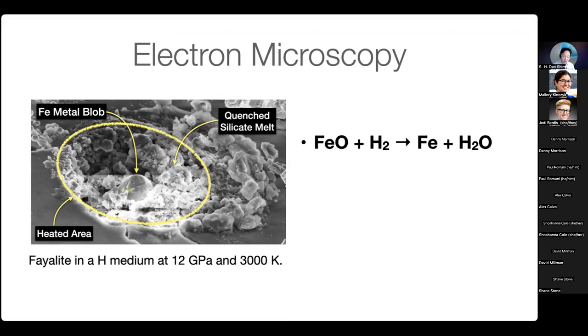To summarize all this into the chemical reactions, we find that oxidized iron reacts with hydrogen and forms iron metal with water. And silicon oxide or silica reacts also with hydrogen and reduces to metal and forms H2O. What is important to note here is that because silicon is oxidized to 4+, while iron is oxidized to 2+, when silicon is reduced to metal, it produces twice more water. And then if you combine the fact that much of the iron is already in reduced form in planet forming systems, and silicon is already in mostly oxidized conditions, silicon reduction should be able to produce much more water than the iron.